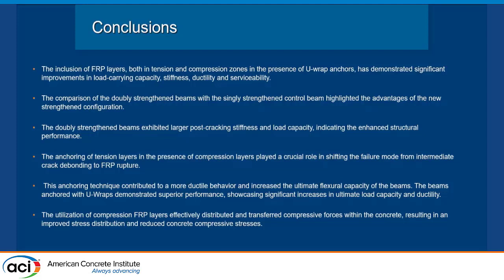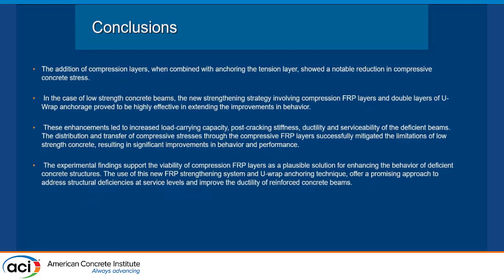So utilization of the compression FRP layers effectively distributed and transferred compressive forces within the concrete, resulting in an improved stress distribution and reduction of the concrete compressive stress. The addition of the compression layer, when combined with anchoring the tension layer, showed a notable reduction in compressive concrete stress.